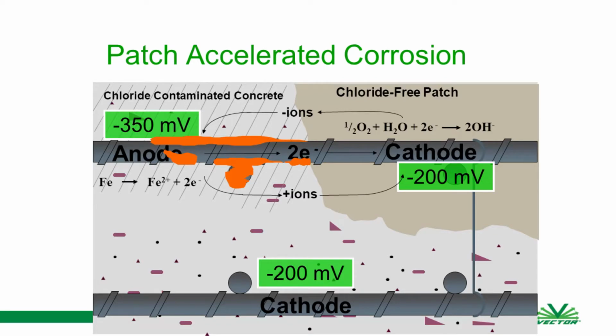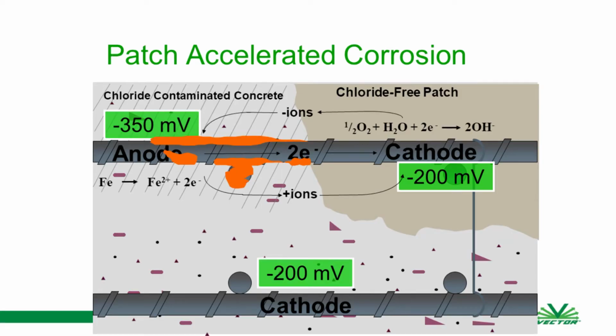So in that patched area, you're back down to a nice passive state where steel wants to be, about negative 200 millivolts. The surrounding areas are still more electronegative due to chloride contamination or carbonated concrete, whatever the case may be. That potential difference between that area within your patch and that area outside of it, you have essentially flipped your anodic and your cathodic site. So what that's going to do is start the whole process over again, and that's where you get that ring or that halo effect. That's what's causing it.